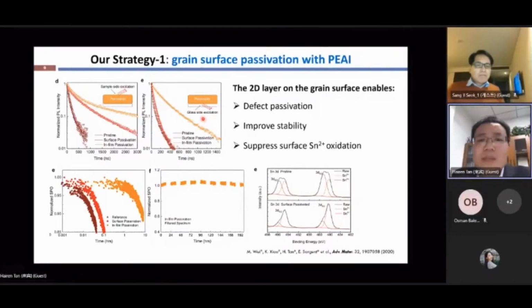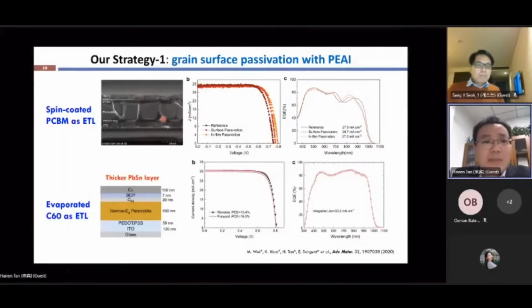Another benefit of this capping layer is that we can much reduce the surface oxidation of the tin 2+ ions. And in this way, we can much improve the performance and also the stability of this narrow bandgap perovskite solar cells. So when we use an absorber layer of 400 nanometers, we can get a higher performance. But we can see from the EQE spectra that due to the very thin absorber layer, the JSC value is only around 27 milliamp per centimeter square.